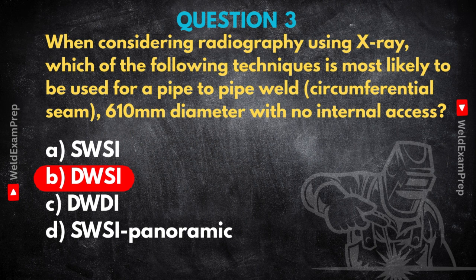Okay, that makes sense. But why not the others? Like, why wouldn't SWSI or DWDI work here? It's not just pick one and go, is it? Definitely not. It's all about picking the right tool for the job, based on the situation. So SWSI, single wall, single image, that usually gives the best image quality. Right. But for that, you normally put the source inside the pipe, aiming out at the film on the outside. Great if you can get inside, but with no internal access on a 610 millimeter pipe, impossible. Okay, so SWSI is out.